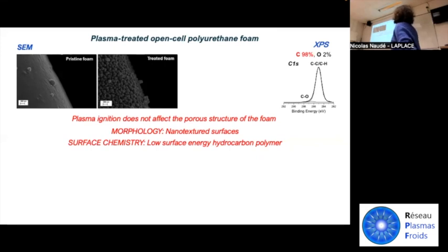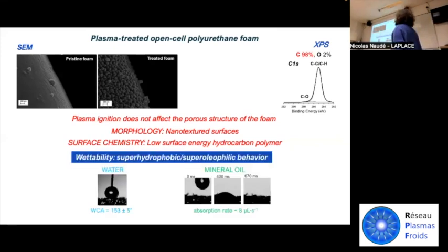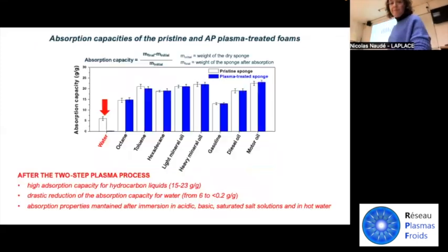And you can appreciate these nano nodules that, in combination with the low surface energy hydrocarbon polymer, and this is confirmed by XPS that shows that the surface chemistry is now dominated by the hydrocarbon polymer, allow us to obtain super hydrophobic and super oleophilic behavior. That is, to obtain wettability selectivity. Now the contact angle for water is greater than 150 degrees, and the foam still absorbs mineral oil quickly.